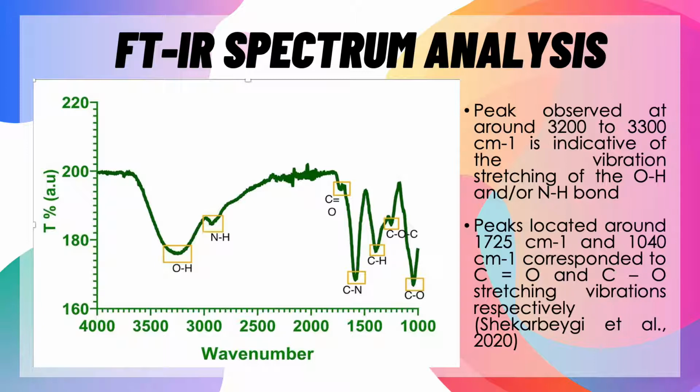After I successfully synthesized the nanoparticles, I ran it through FTIR first, and I discovered that under FTIR there was a peak observed at around 3200 to 3300, which is indicative of the stretching vibration of the OH-NH bond. This indicates that the carbon dots are hydrophilic.